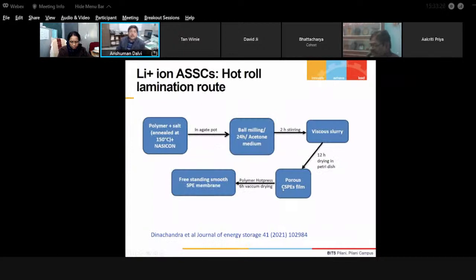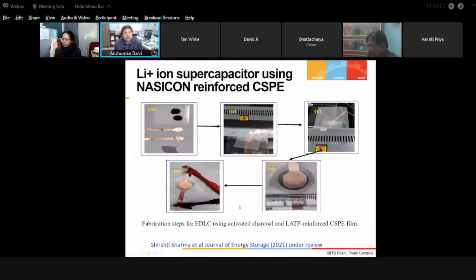The next job is to talk about the fabrication of these supercapacitors. Here we have to ensure that the electrolyte is very, very uniform. That means the solid electrolyte membrane we are preparing has to be uniform, so that the thickness remains the same everywhere and interfacial contacts are possible. Here a ball mill assisted synthesis route was used by us to prepare this freestanding solid polymer electrolyte film, not the conventional route. Then we used a simple hot roll lamination process, sandwiching the electrolyte membrane between the high surface area carbon electrodes.